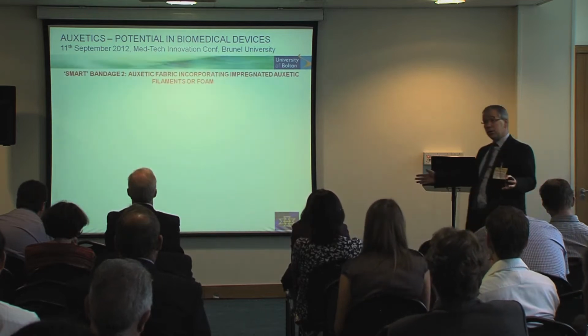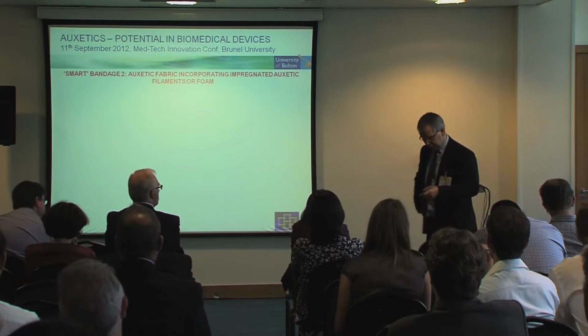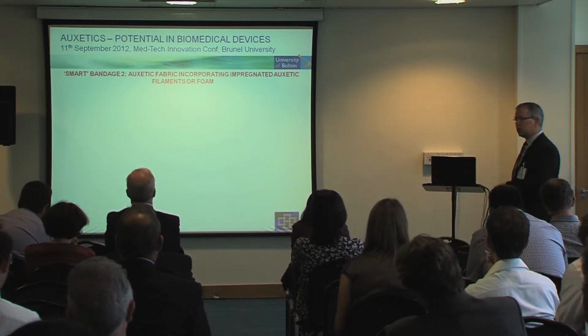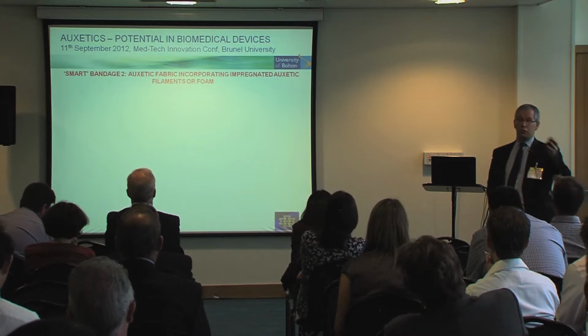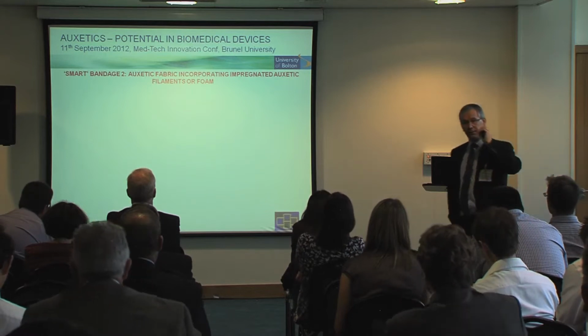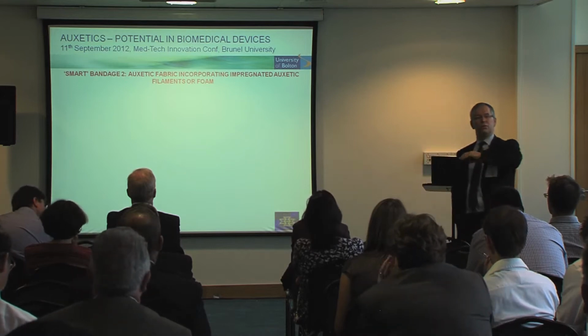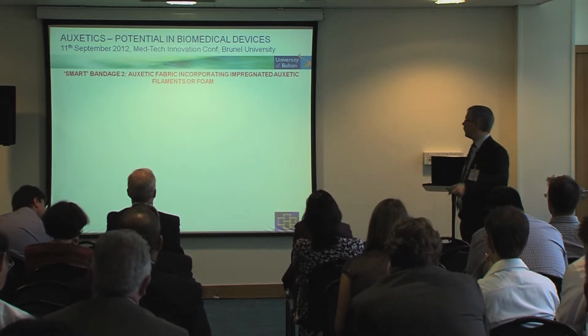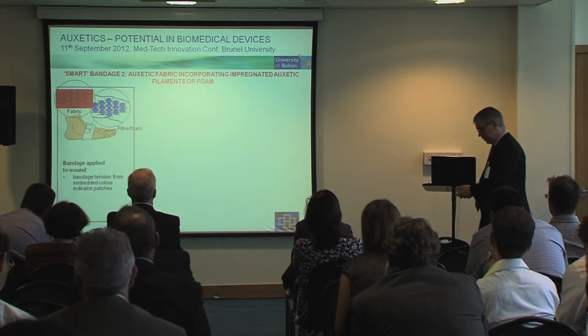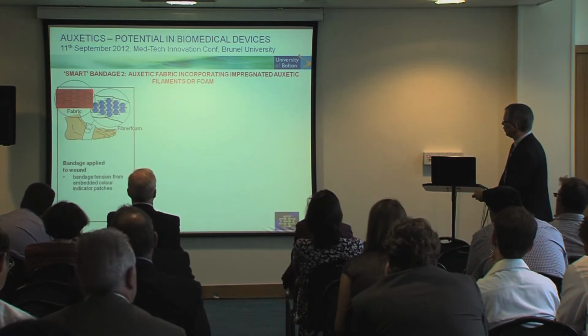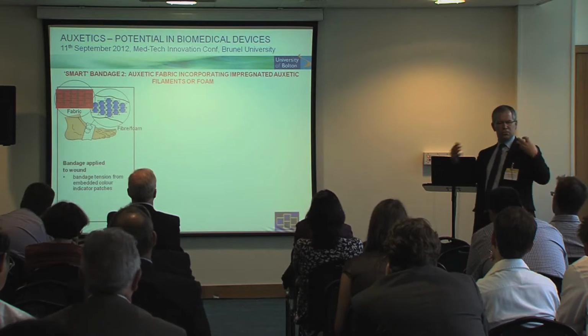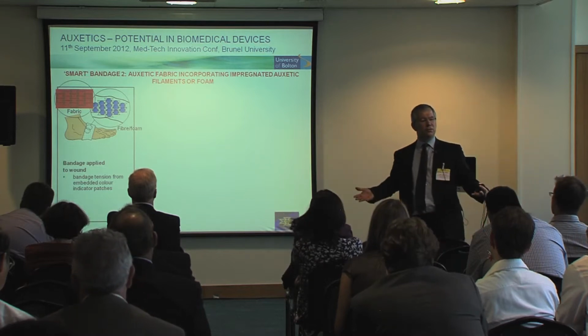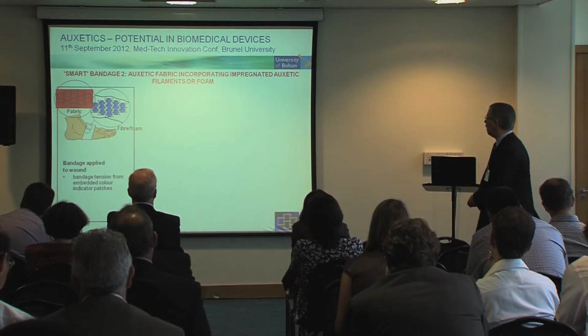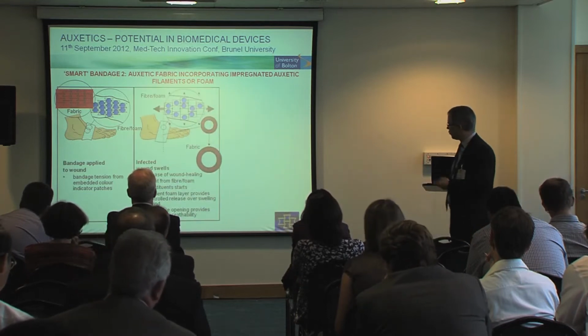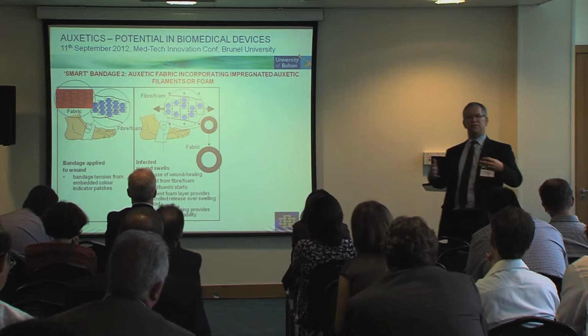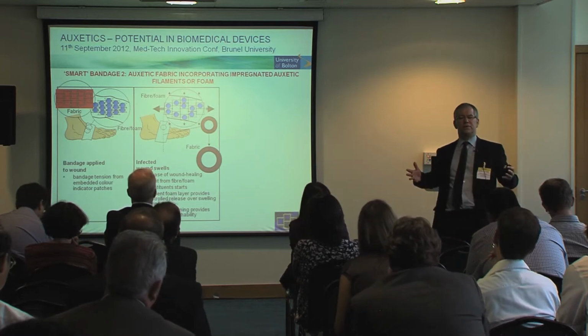So we can now look at a second generation multifunctional type of bandage application. We've now got not just auxetic fibres or auxetic foam as the component hosting the active ingredient, but we've also got an auxetic fabric structure. Okay, and we can, at the fabric scale, have colour patches put in there, so the nurse who's applying the bandage can tell when it's got the right tension, it's changed to the right colour. Yeah. And now, when the wound swells, not only do we activate release of the drug, but we have more control over that release if it's a gradient structure.